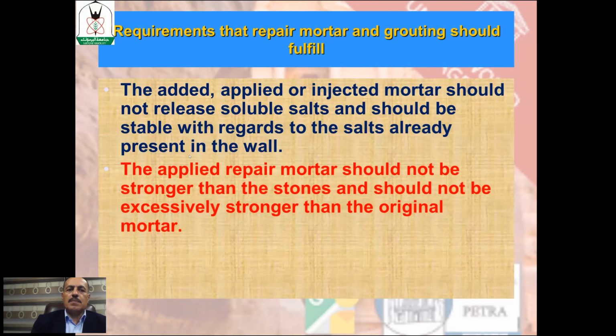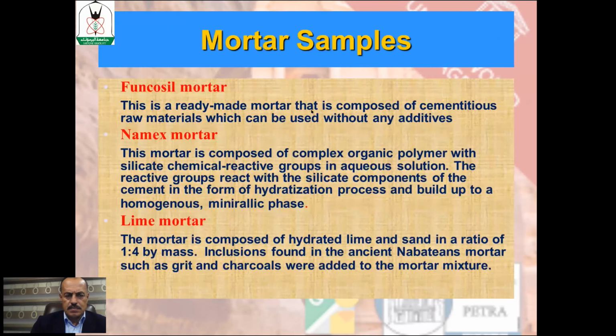So for example, the performance criteria include that repair mortar should not be stronger than the stone and should not be excessively stronger than the original mortar. And it shouldn't release or emit soluble salts into the stone and structure. And again, we selected a number of mortars: two commercial mortars and a lime mortar that we prepared based on our analysis of the ancient mortar used by